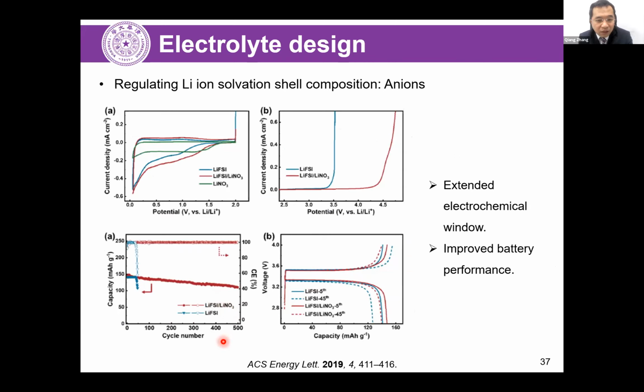This can also be observed in the electrochemical test results, in which, with the lithium nitrate addition, the cell shows less electrolyte decomposition, and if we try to record the working window, it is found that it can be enlarged from 3.5 to 4.5 V. So this helps the electrolyte match not only the sulfur cathode; the nickel manganese cobalt oxide system can also be applied in this case.